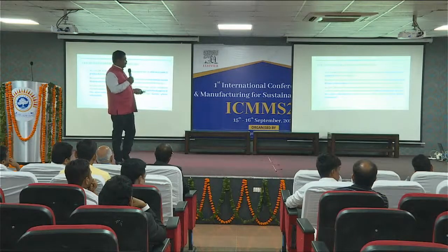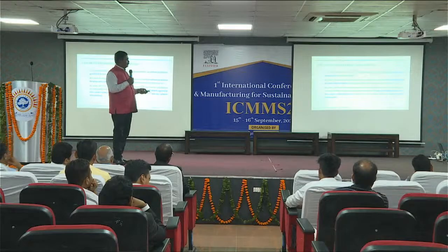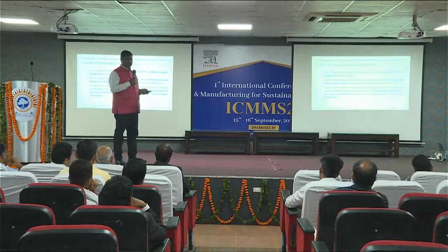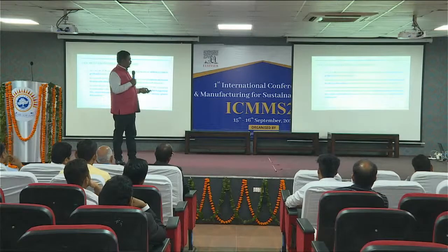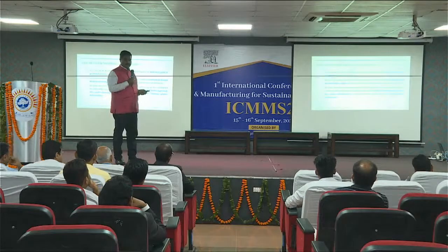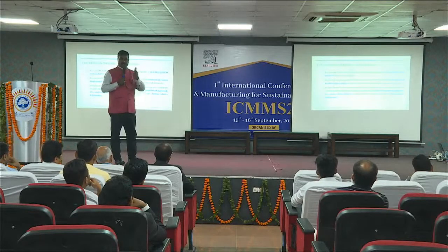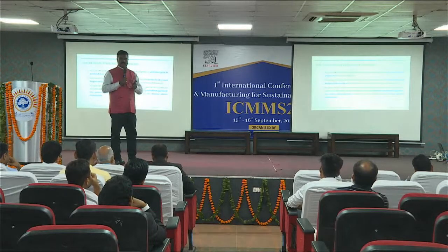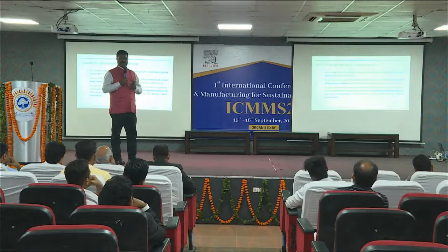Because of various geometrical features, the tool material movement around the pin can be complex. So a fully recrystallized equiaxed fine grain microstructure is obtained. Suppose you take the specimen, cut through it and do microstructural testing, then you can find out that a very refined grain size is obtained.